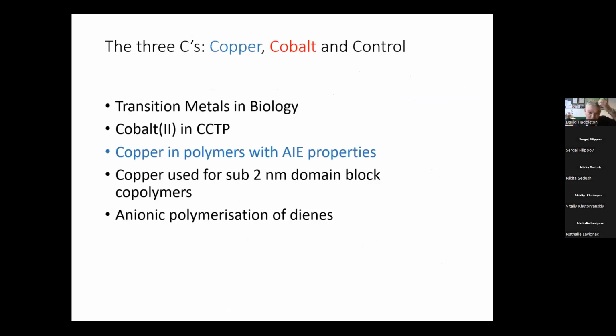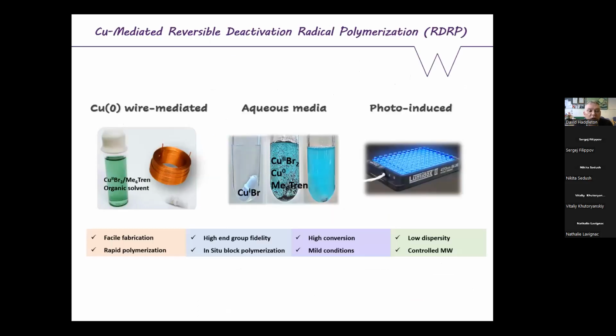So I'm going to move now from cobalt to copper, and 2 little stories about how we use copper. We use copper in 3 different ways. So we will use copper 0 with copper wire, and I'll talk about that. And we're normally using hexamethyl tren or a tertiary amine ligand in an organic solvent. We use it in water, which I like a lot, where we use copper 1, but the copper 1 disproportionates, and I'll show you that on the next slide, actually, to copper 0 and copper 2. We have to wait for it to disproportionate, and then we're using copper 0 again. So here we use copper 0, here we use copper 0. None of them are copper 1.